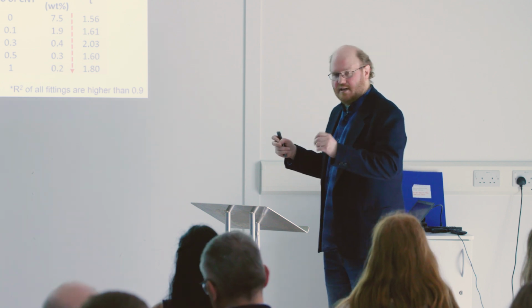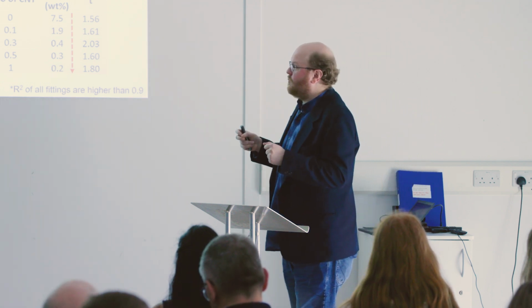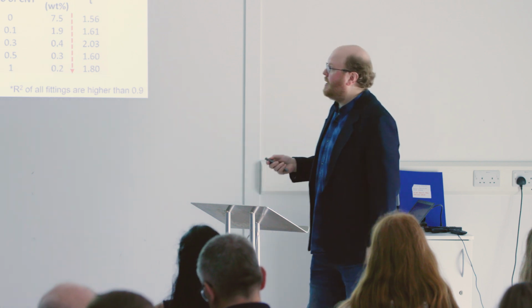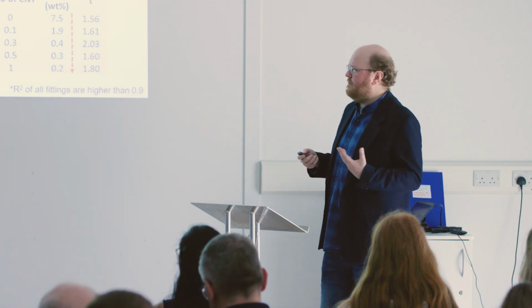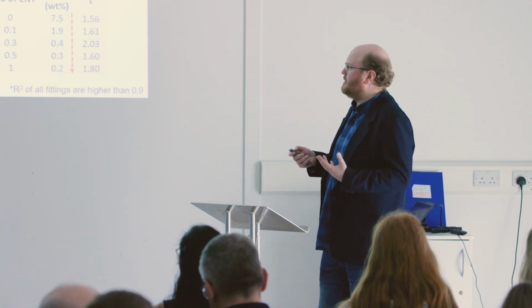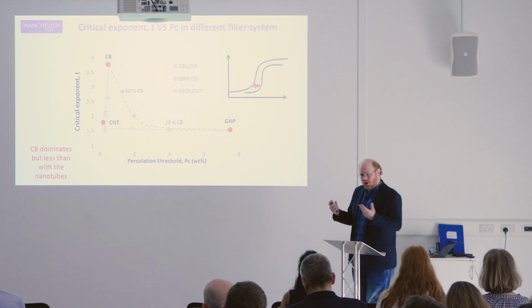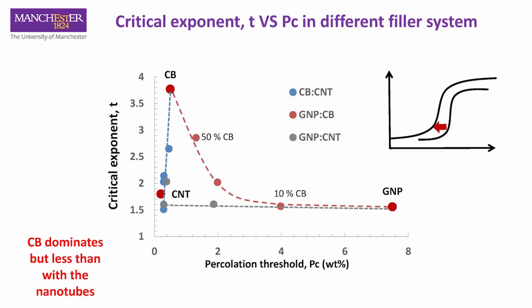Is it purely just a sum of the parts, where if this one gives us this conductivity and this one gives us this, we meet halfway in the middle? Or is there an unexpected benefit by having the two of them interact with each other? That allows us to make a curve that looks like this, where out here you've got 100% GNP, down here 100% nanotubes, and up here 100% carbon black. The data points in between are the different ratios.